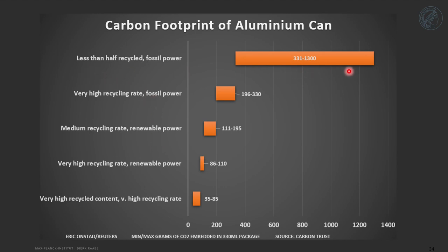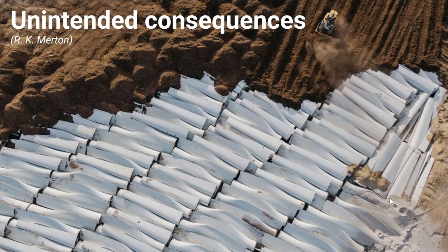Look at the upper bound, which actually does not look so good, from the CO2 emissions. This is an example where the can was produced by only less than half recycled material that was being used in the melt and by the use of fossil power. The best case scenario is when you have a very high recycled content and likewise use a very high recycling rate after usage of the can. And you see, this relationship, which goes down to about only 5% in the best of all worlds, relates roughly to the relationship between the aluminum oxide embodied energy when you produce the material mainly from the raw material, as opposed to the relatively low electrical energy that you need when you remelt the material from scraps, because aluminum has a relatively low melting point with only 660 degrees centigrade.